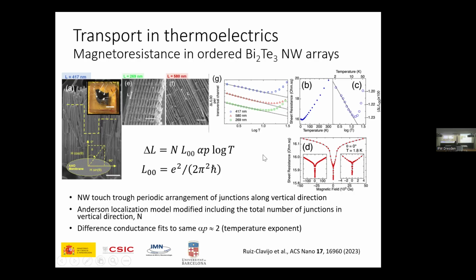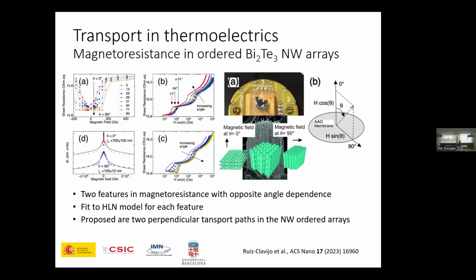So what we did, and this is the example here, is perform angle-dependent measurements of that object, shown in the picture. And then we studied the evolution of the magnetoresistance signal of these two dips with the angle to the magnetic field, right? In one case, we saw that the lower dip, or the internal dip, scales with the cosine, the vertical projection of the magnetic field, and the other scales, or collapses, with the sine of the angle. So that gave us the idea that these two dips, or weak anti-localization features, are related to two geometrical directions perpendicular to each other in the structure, which according to what it looks like would be vertical along the wires themselves, and the other one transversal from wire to wire, in what more or less looks like a Swiss cheese kind of structure.